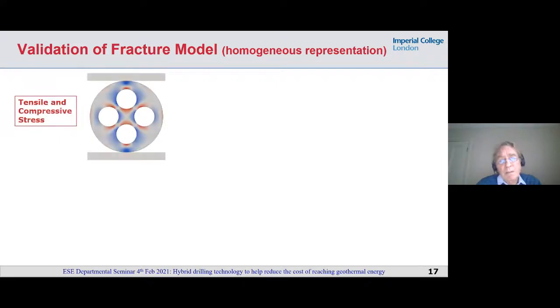And I just want to spend one slide on this really nice work by Ardo Farsi, looking at the validation of the fracturing that we have in this code. This is actually a ceramic disc with 4 holes in it, and this is a numerical simulation showing the compression of a disc with 4 holes. You can see in blue the compressive stress field, and in red the tensile stress field during the early stages of loading.